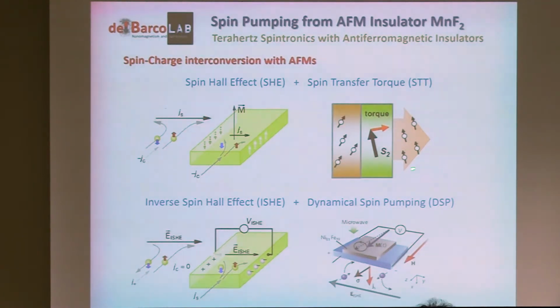The other technique that usually is made to work together with the first one is the spin transfer torque. So now let's imagine that we have in a spin current a certain accumulation of spin in a material, basically spin polarized electrons moving in one direction. Then you get into a ferromagnet in where you have magnetization, and then because of that interaction, there will be a magnetic torque that is going to try to move the magnetization of the ferromagnet, in this case, into a given direction, or even induce that ferromagnet to get into a precession and induce dynamics, right? When you combine the two, you can start manipulating and controlling your spintronic device. And this has been demonstrated for ferromagnets.